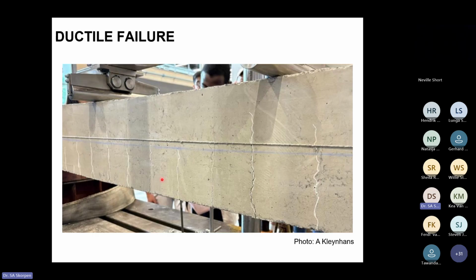And this is something we do every year with our third year class. We test basically 3 different beams to failure. We first test an under-reinforced beam to failure, and then an over-reinforced beam to failure, and then we also look at a shear failure, which I'm not going to talk about today. This is just showing a ductile failure mode. You can see this fairly uniform distribution of cracking, which is typical of something that's busy working in bending.